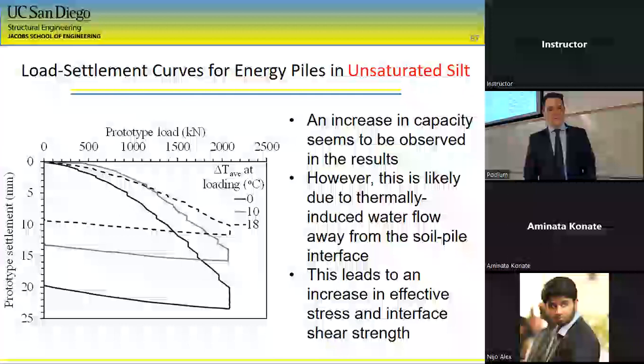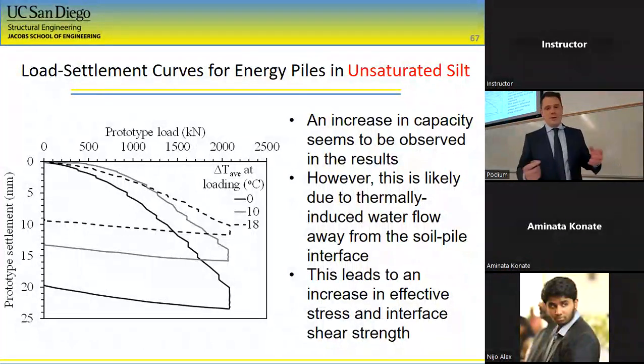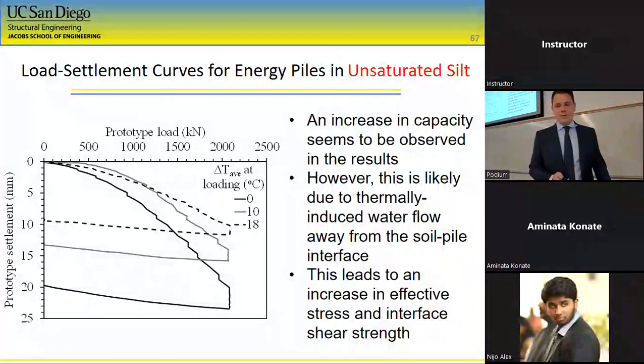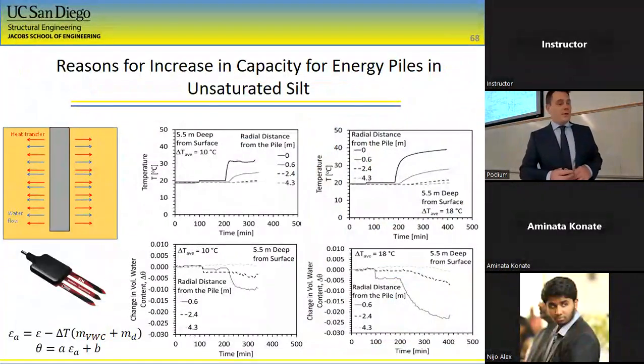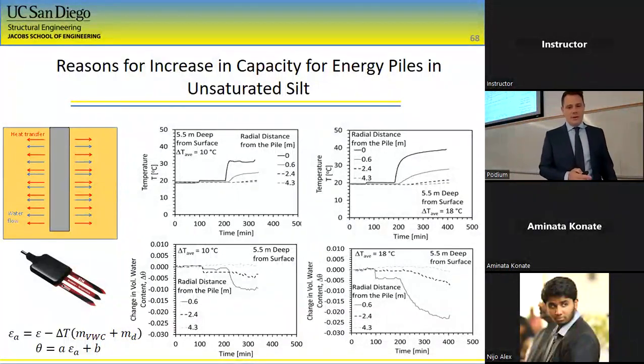But when we went on to the unsaturated soils, we saw a big increase in capacity with temperature. We didn't load these all the way out to failure, but we can extrapolate those with hyperbolic models to figure out what the actual capacity was. So we hypothesized that this was due to heating and drying of the soil. And we actually put some sensors into the soil at different locations and found that as the temperature increased, the soil dried out. So we wanted to do some modeling to figure out what the conditions are right at the interface, because you can't put a sensor right at the interface.